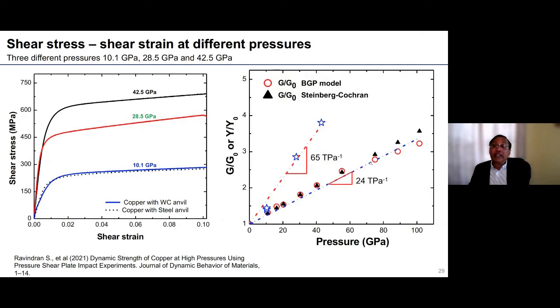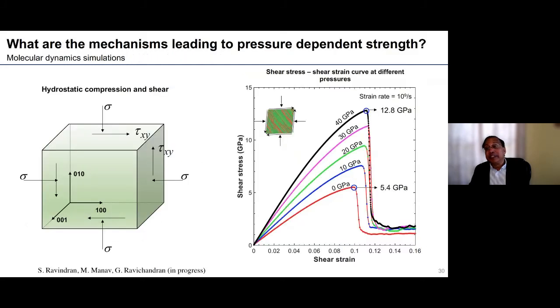As I mentioned, the conventional Steinberg-Guinan model assumes that we have the same dependence of the shear strength and the yield strength. But what we observe is that the yield strength changes considerably with respect to pressure, as opposed to what is normally assumed in the Steinberg-Guinan model or in the literature. So I think this is a new finding because we make these direct measurements.